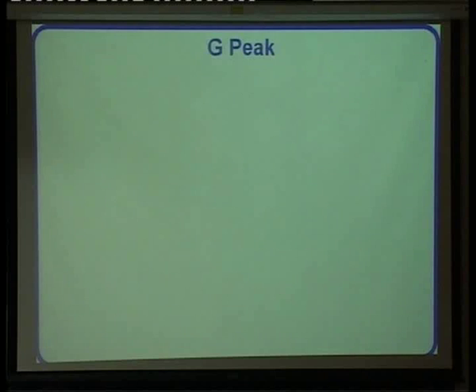We thought for many years that the G peak was very easy because the G peak is the Q equal to 0, so it's what is Raman active normally, and there should be no particular science in it. And it's the standard peak. It's called the G peak because when you take a piece of graphite, you stick it in a Raman spectrometer, press a button, you see one peak, and it's graphite, you call it G, okay? That's the whole story of the G peak. No particular science in it.